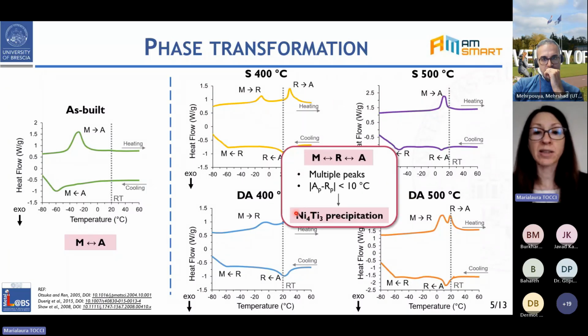This is especially evident for the treatment carried out at 400 degrees. Then it was also possible to observe that for almost all cases, as compared to the As-built condition, the transformation does not take place in one step, but in two steps, since we identified the formation of an intermediate phase indicated as the R phase, which suggests the formation and presence of Ni4Ti3 precipitates. It is known from the literature that the presence of the R phase is enhanced by the presence of these precipitates. So this was a further indication that the heat treatments tested were effective in shifting the transformation temperature and in allowing the formation of these precipitates.